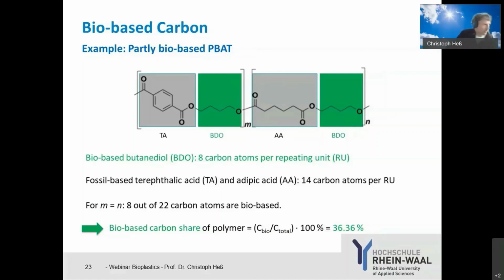And now we can calculate the bio-based carbon share, which is defined as the number of bio-based carbon over the total number of carbon times 100%. That here sums up to 36.36%. So slightly more than one third of this partly bio-based PBAT is really bio-based, referring to the carbon, because we can measure radioactive decay and the carbon-14 share in this material.